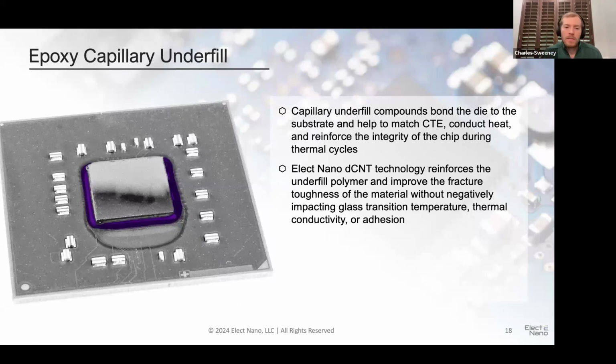There's air in between the solder bumps, and there's a big CTE mismatch, coefficient of thermal expansion mismatch, between the die and the substrate. That leads to a lot of stresses that build up as these devices thermally cycle. The typical way to at least address the issue is to use something called an underfill, where you basically trench and then allow the adhesive to wick underneath the chip and the substrate. These are high flowability epoxies that are very highly loaded with silica filler in order to match the CTE between the chip and the substrate. It helps to relieve stresses so that you don't break off your solder bumps during thermal cycling.